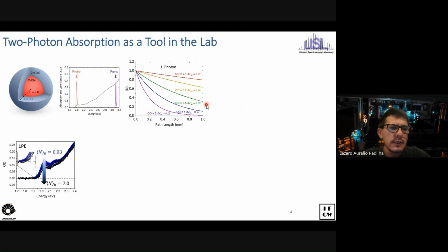Let me just give you an example. If you're studying optical gain in nanomaterials by exciting by 1-photon absorption, this is a sample with optical density at the pump of nearly 1. And you see that you're hitting 7 excitons per dot on the front surface, and you barely see gain here, okay? And that's because for your high optical density, you're basically depleting through all your sample path, and you're not seeing gain.